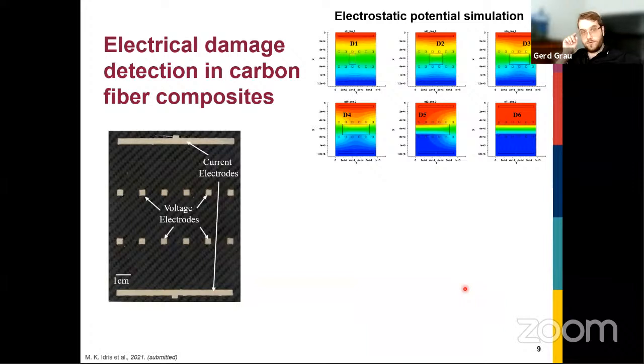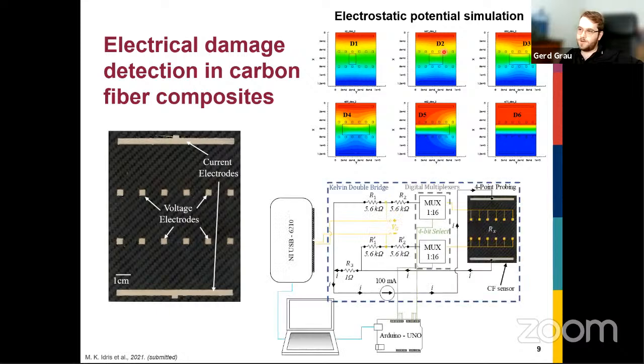We also use this to detect damage and strain in a carbon fiber sheet. So we printed some current electrodes. We inject current here into our sheet, and then we can measure voltage at different points in the sheet. And you can see from this modeling, if we have puncture damage, for example, this rectangle, we also looked at smaller damage, but you can see that it disrupts the potential, and then you can measure this as voltage. And we designed an interface circuit, and that allowed us to actually detect where the damage is inside this carbon fiber sheet.